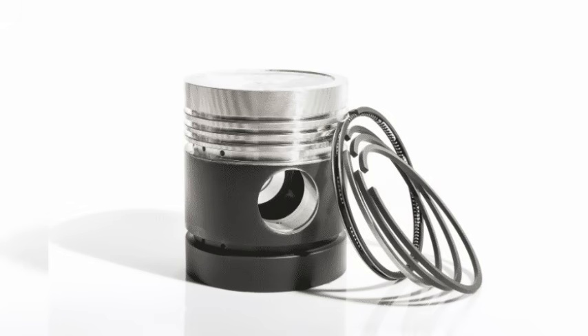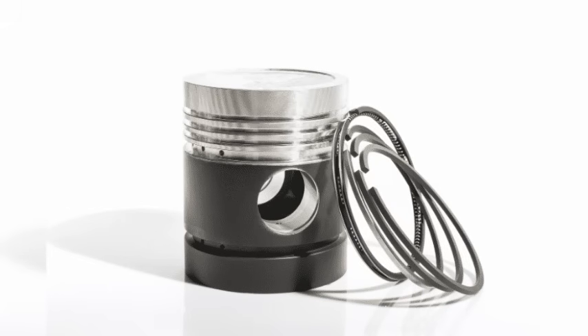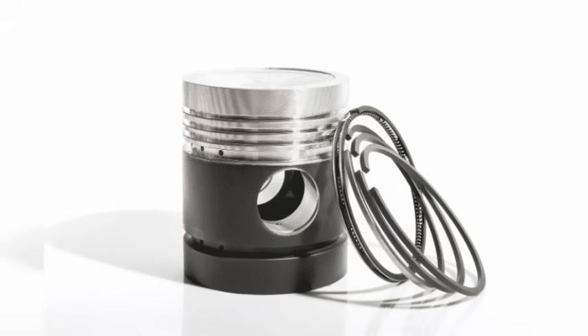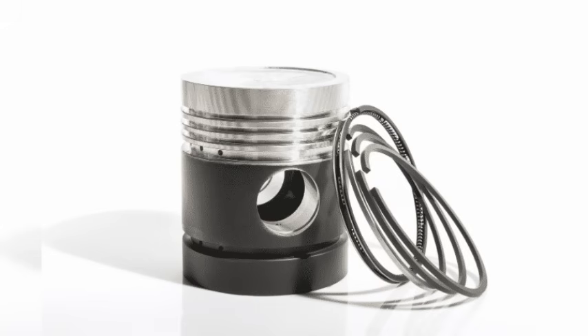Challenge 2. Adhesion. Chrome had to bond strongly to the iron substrate. In decorative work, if plating peeled, it was cosmetic. In an engine, peeled chrome would destroy the cylinder in seconds. Hastings engineers developed surface preparation techniques, careful cleaning, specific etching processes that promoted strong adhesion. They also experimented with undercoats, thin layers of other metals like nickel, that improved chrome bonding.